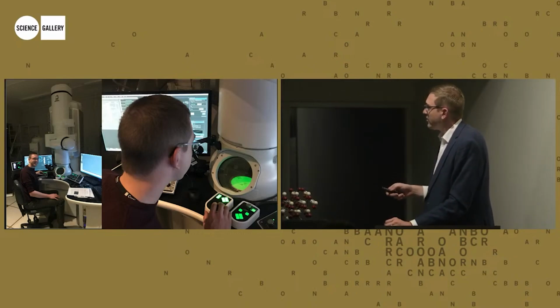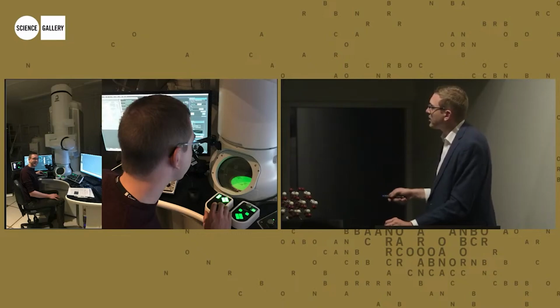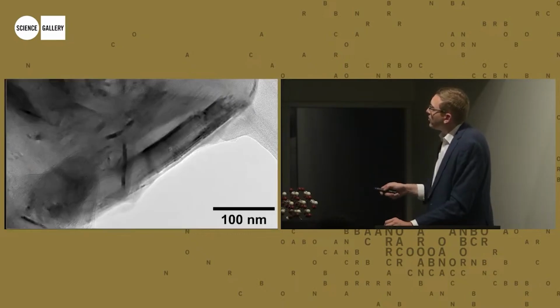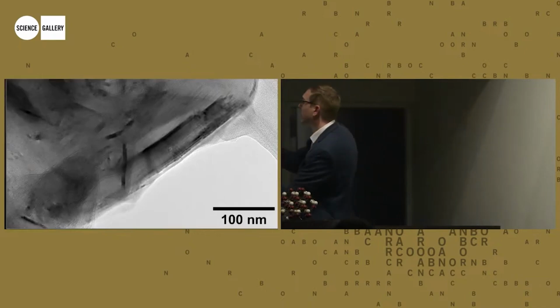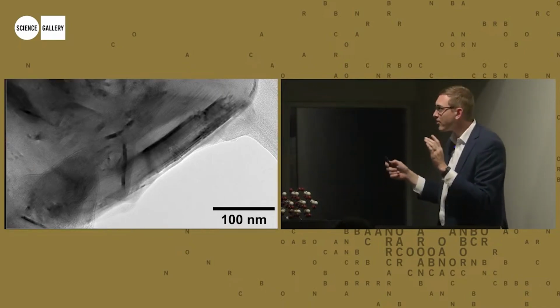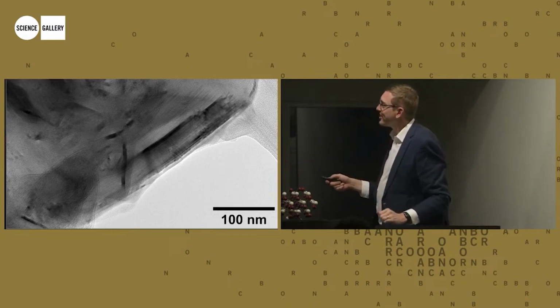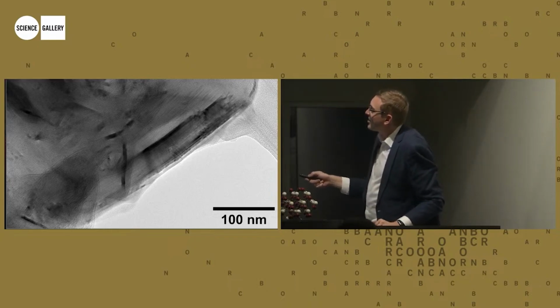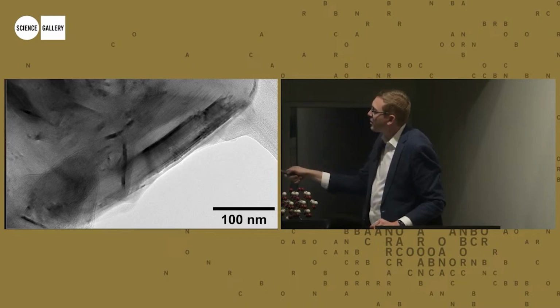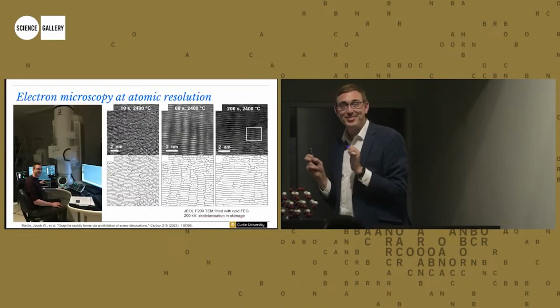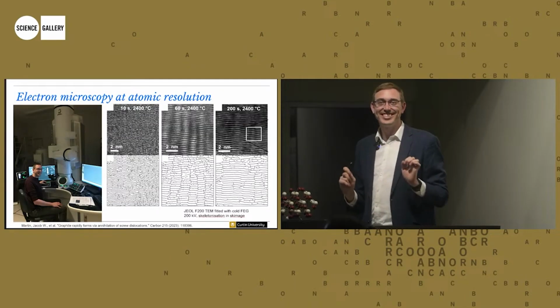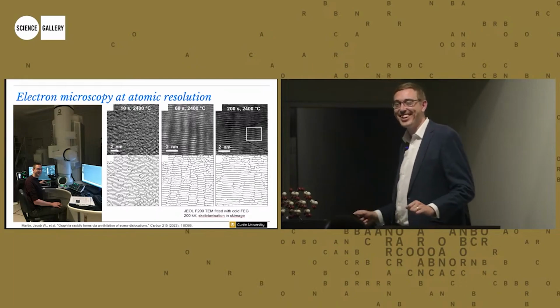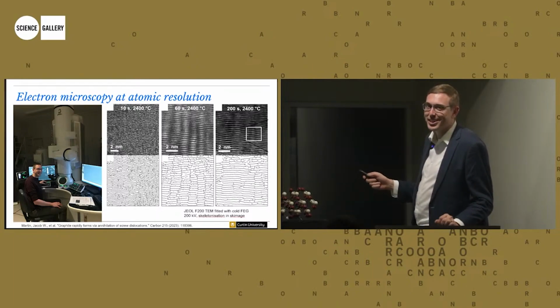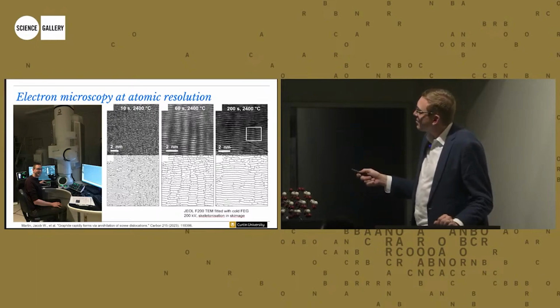And so we looked at graphite. So here is a crystallite of graphite, and those are the layers like this, but we can zoom in, enhance. So this is it enhanced. This is after a single pulse for 10 seconds, a 10-second pulse. And you can see that there's an alignment. Can you sort of see the dots as well, the little dots? Those are carbon atoms, like individual carbon atoms, which I just think is so cool. Anyway, I get really excited about seeing atoms, particularly carbon atoms.